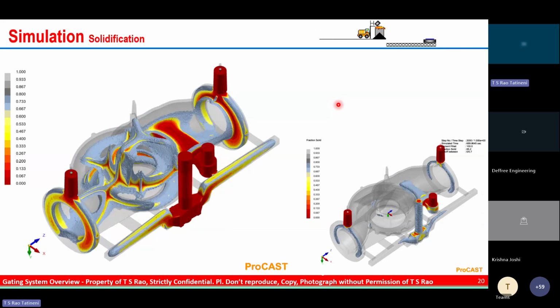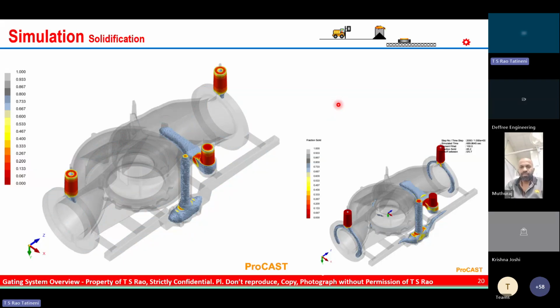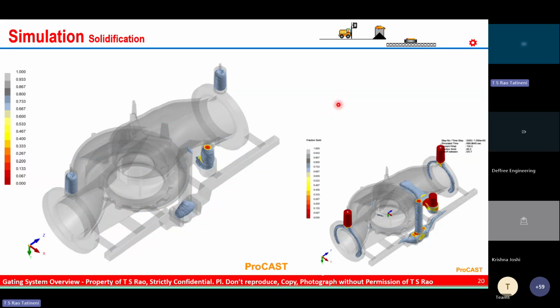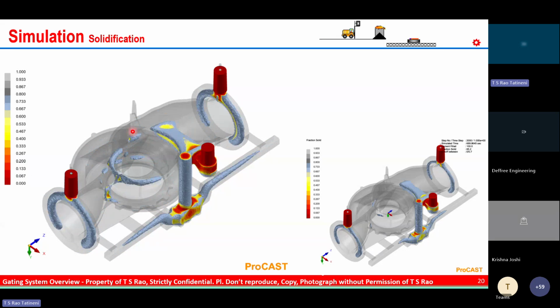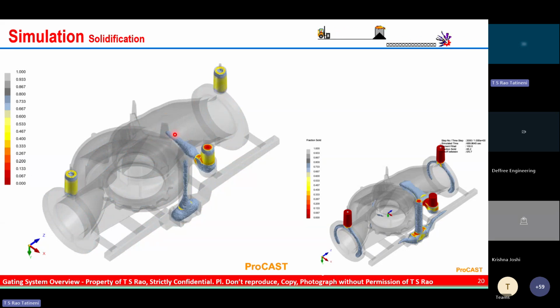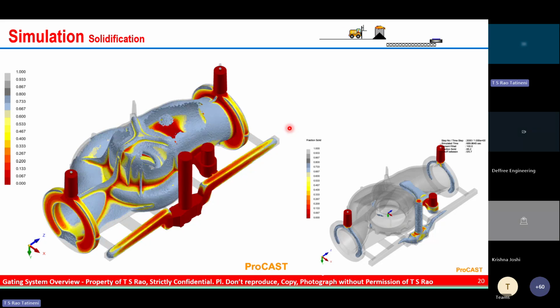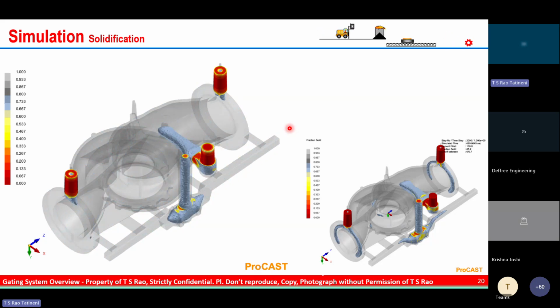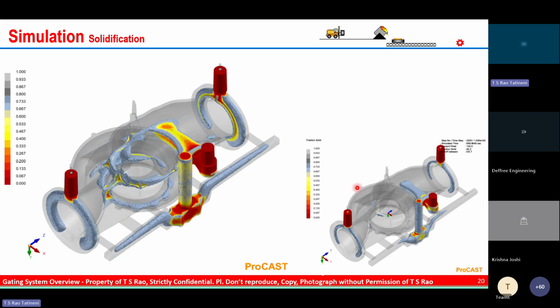The next slide is on the solidification. Directional solidification is very important. The last freezing zone should be close to the riser to ensure that the riser is hot till the entire casting is solidified. This solidification pattern shows how the casting is directionally solidified towards the risers. It ensures that there is no hot metal left without feeding by the respective feeders. See, the last freezing zone is in the risers. Here you can see how the directional solidification is happening within the mold environment.